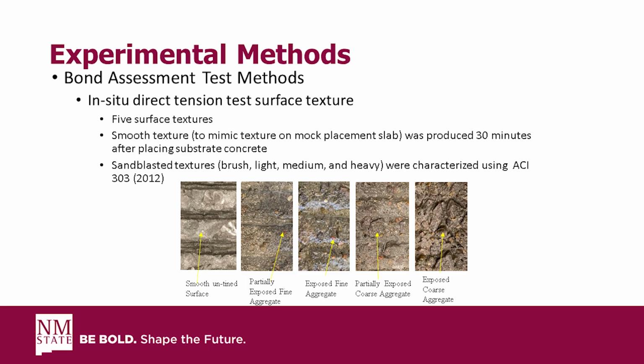That's partially exposing the fine aggregate of the substrate. And then we go into the light sandblasted texture, which exposes the fine aggregate, the medium sandblasted texture, which partially exposes the coarse aggregate, and then our roughest texture is going to be our heavy sandblasted, which exposes coarse aggregate. You can see those in the bottom images here.